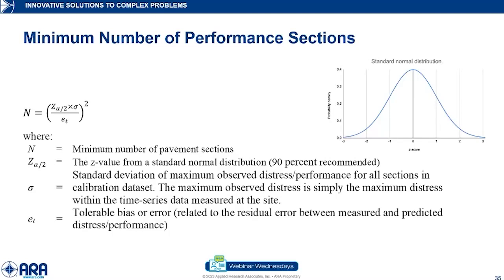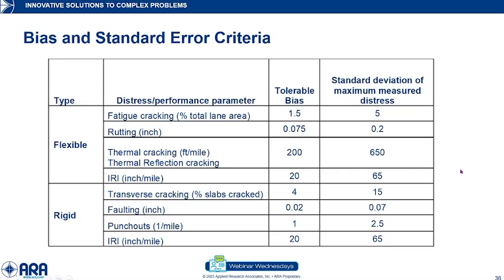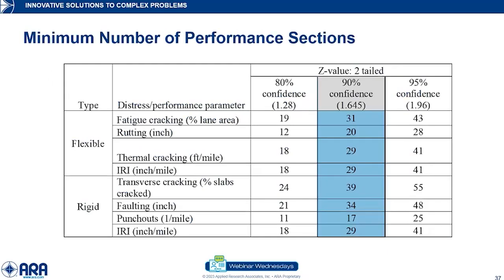And then finally, the tolerable bias, which is related to the residual error, the difference between measured and predicted distress performance. Fortunately, you don't have to figure this out. It's already been done for you, and this was done during the global calibration of the pavement ME design program. These were the numbers generated for the bias and the standard deviation and maximum measured distresses for each one of the distress models they're showing for flexible and rigid. So we basically have what we need to run that calculation.